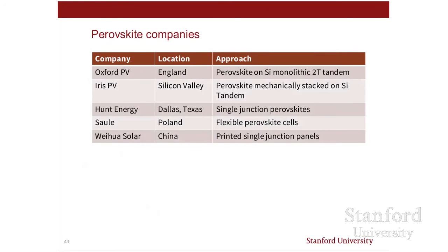There are 5 companies that I know of in the startup stage. Oxford PV is certainly the largest, and they're developing a 2-terminal tandem with perovskites on silicon. Full disclosure, I have co-founded Iris PV with Colin Bailey, and we're taking a different approach. We are mechanically stacking perovskites on silicon. Hunt Energy, led by Michael Irwin in Dallas, is going with single junction perovskite, so they're going for an ultra low cost product. And Saule in Poland seems to be doing flexible perovskite cells. I don't know a lot about Weihua in China, but I have seen pictures of panels almost 2 feet across that they've already been able to print.